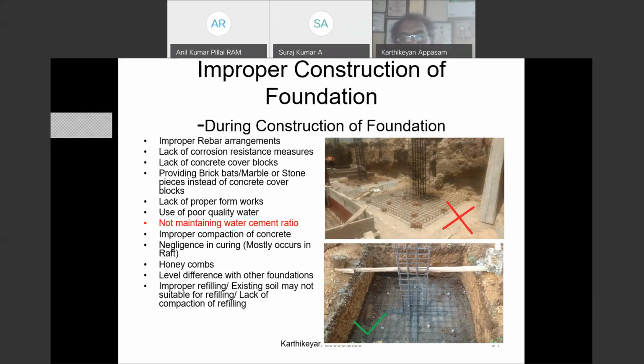One of the most awkward scenarios we found is this fellow very nicely fabricated the steel, the pedestal, the column, everything. But he put bricks instead of cover blocks. In one of the sites, I scolded people, don't put bricks, use cover blocks only. The next day he put fly ash blocks. He argued that this is also grey color. Color is not important, content is important. Because when you put concrete on this, the bricks get crushed. When the bricks get crushed, there is a chance of moisture ingress, and then the reinforcement gets corroded.